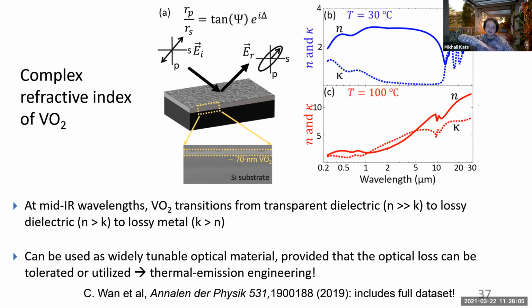You can copy and paste it into any of your electromagnetic simulations, for example, because we couldn't find these data sets. And so we made our own for VO2 as a function of temperature throughout this phase transition. And you can see that the change is very, very dramatic. In fact, the material goes in the mid-infrared from being a low loss dielectric type material to being like a really bad metal. That would be what you would call this.